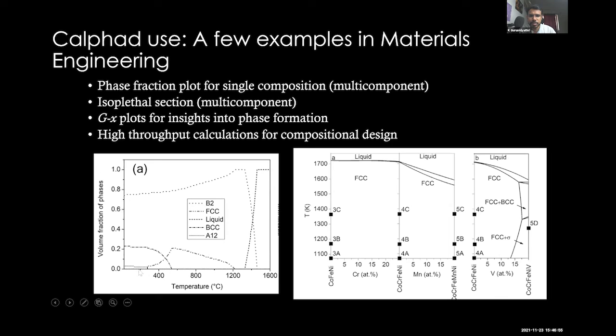Here, with respect to temperature, volume fraction of phases is plotted, which means in one composition, 5 elements, single composition, if you change the temperature, different phases will come into equilibrium. I mean, different phases will be stable phases in the microstructure. And what are those phases? This label tells you the name of the phases, crystal structure also. And what is their amount? That can also be directly read from this y-axis. So that is one representation. This is called a phase fraction plot.